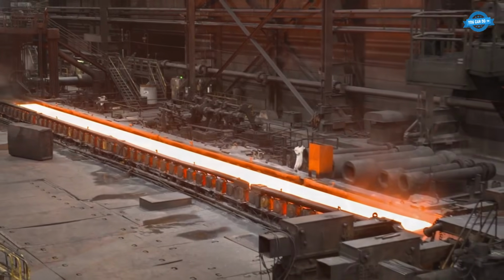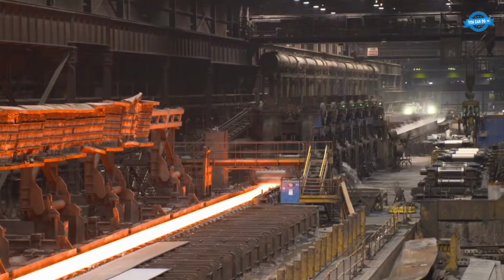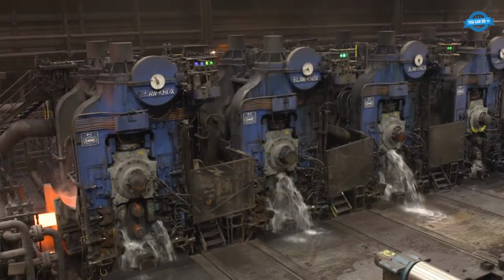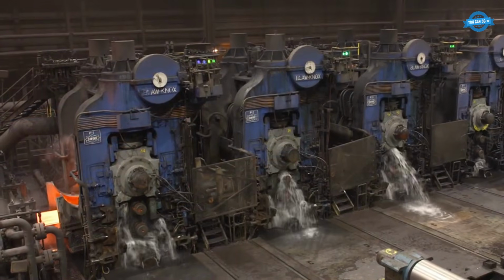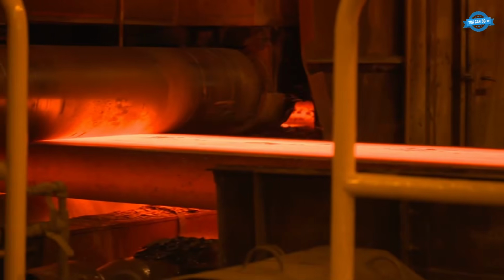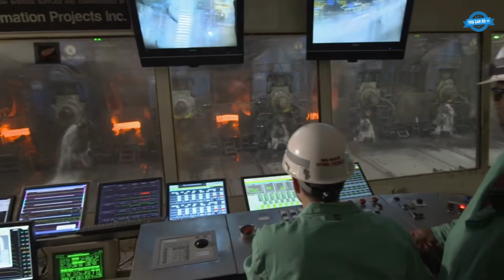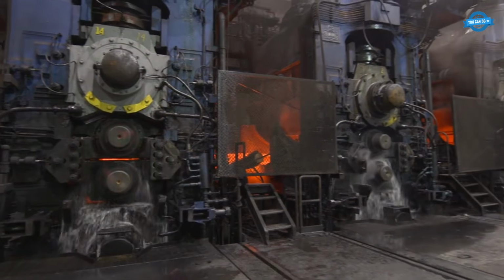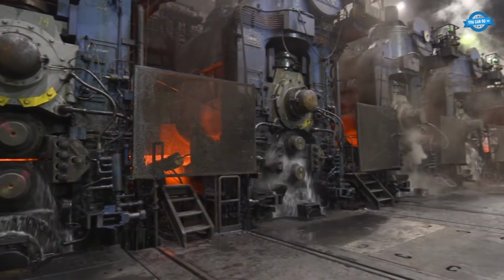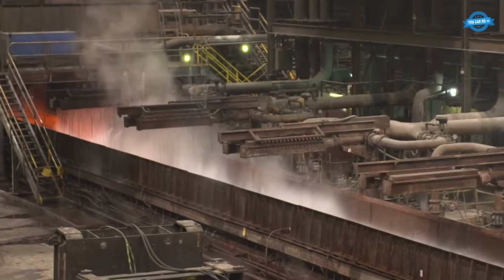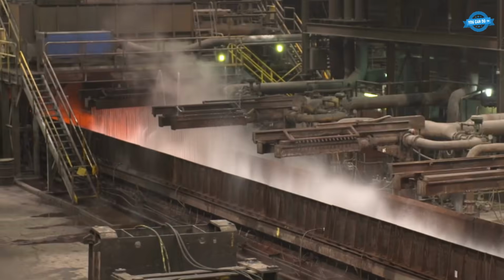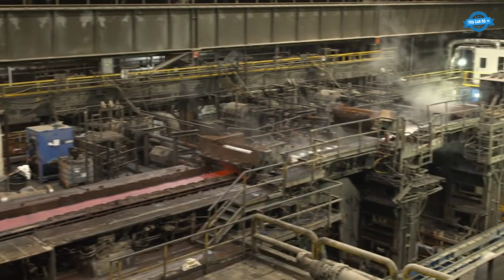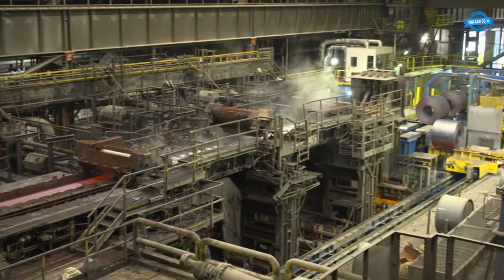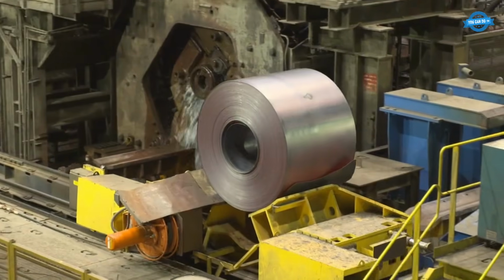Liquid steel then pours into continuous casters, gets cooled by copper molds and water mist, and comes out as an 8-inch thick slab. Slabs get reheated to over 2,300 degrees, hammered down in a roughing mill and stretched out in a 7-stand finishing mill until an 8-inch slab becomes a 4,100-foot ribbon of steel. Watch a slab enter one end and coil out the other in minutes. And the whole point of this video finally lands.